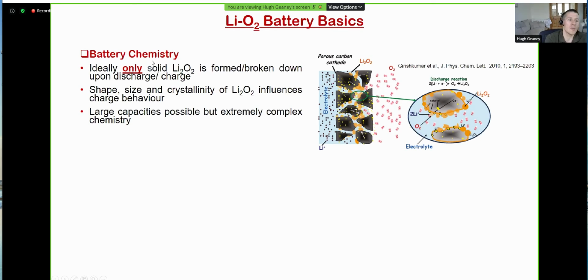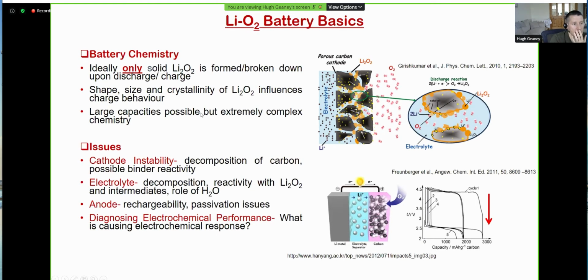So what we have is, ideally, all we want is solid lithium peroxide formed and then broken down on the discharge and charge. But as a result, we now have a solid product within our battery. So the shape, size, and crystallinity of that lithium peroxide is going to completely influence how the battery charges as we break that down. So in general, with lithium-air, we have large capacities possible, but it's a very complex reaction chemistry. Even if we just have the sole lithium peroxide formation and decomposition, it's quite complex.